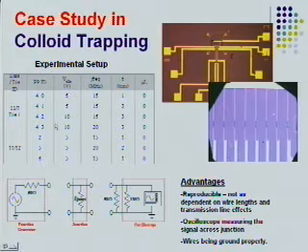Here are the conditions we used. You can see the voltage peak to peak of the AC field, 5, 10 volts typically, and our frequency in the megahertz. We clearly didn't know how to endpoint at first, so we were endpointing by just a certain amount of time. And then we just used 8 microliters. It was important because here's our proximal probes and here's our structure. So you can see this right in here, and they'd be trapped inside.